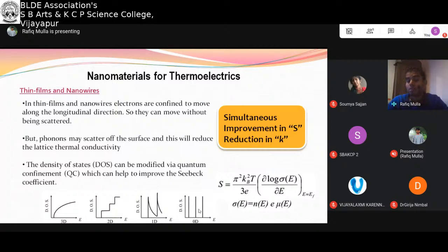Of course, with quantum dots one can also achieve improvements, but they are not practically useful because single quantum dots we can't use for the application. But for study purposes, one can study them using very high-end techniques, but they are not suitable. But nanowires and thin films are quite suitable, though nanowires, again, are difficult to handle. But efficiency wise, we can see the improvements.